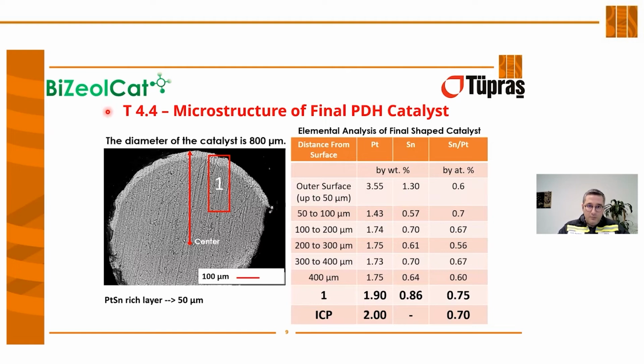So you can see the microstructure analysis of the final PDH catalyst. This is the cross-sectional analysis of our catalyst. We can see the outer side and the inner side of the catalyst. This is the typical distribution of metal on the support. We have a rich layer of platinum tin on top of the catalyst, and as we go toward the center of the catalyst, the platinum tin concentration decreases.